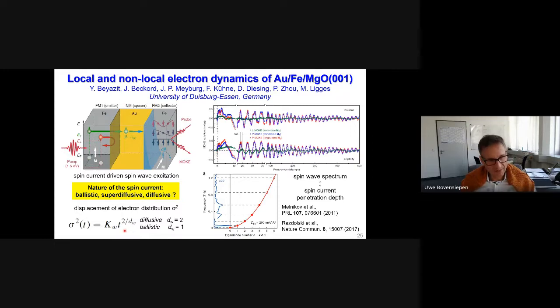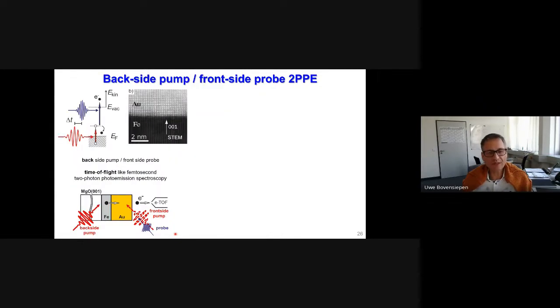So what you have to keep in mind is that one should discuss the displacement of the electron distribution, sigma square, as a function of the respective time. And this is the diffusion constant. And to distinguish between ballistic and diffusive propagation, one has to consider here the exponent on the time. And this dW, this is the anomalous diffusion exponent. So for dW equals to 2, it is just linear, so sigma square becomes linear in time, and this is diffusive motion. But for dW equals 1, you have a behavior of t to the square, and this is ballistic motion. And super diffusive is basically an intermediate regime of propagation.